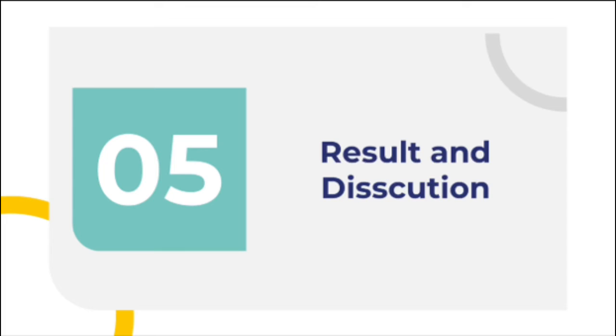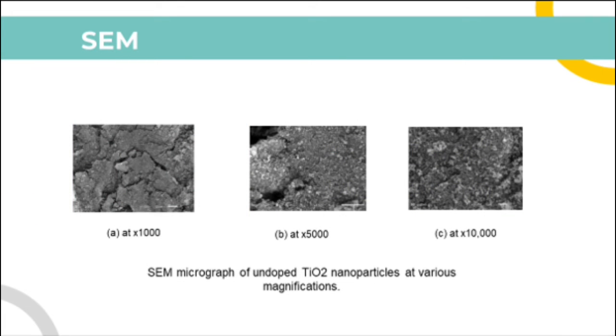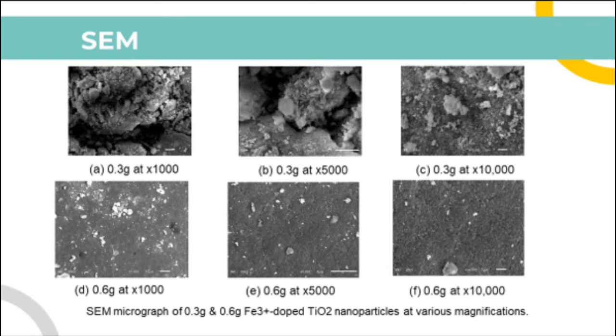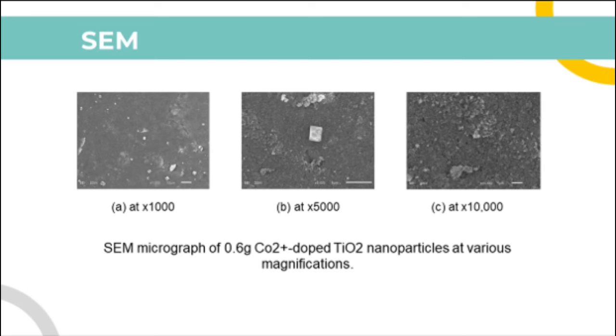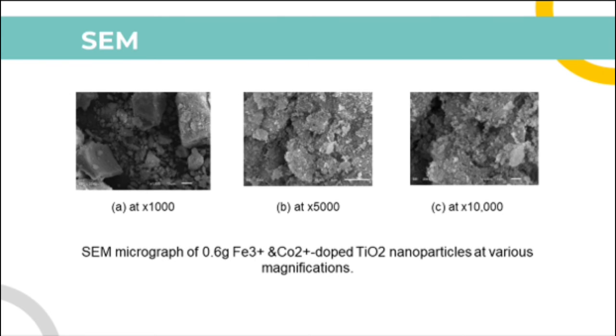This is the result that we got from our project. This is the scanning electron microscopy analysis at different magnifications: 1000, 5000, 10,000. As shown in the micrograph, the morphology of the titanium dioxide nanoparticles is generally spherical, and the nanoparticles are agglomerated together to create several nanoclusters. And these are the SEM analyses of the Fe-doped titanium dioxide material at various Fe³⁺ dopant levels, 0.3 gram and 0.6 gram. Also, these are the SEM analyses of the cobalt-doped titanium dioxide material at 0.6 gram Co²⁺ dopant level. In addition, these are the SEM analyses of the Fe and cobalt doped titanium dioxide materials at 0.6 gram dopant level for both Fe³⁺ and Co²⁺.